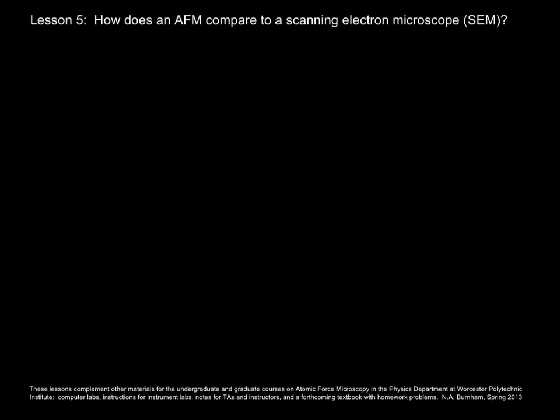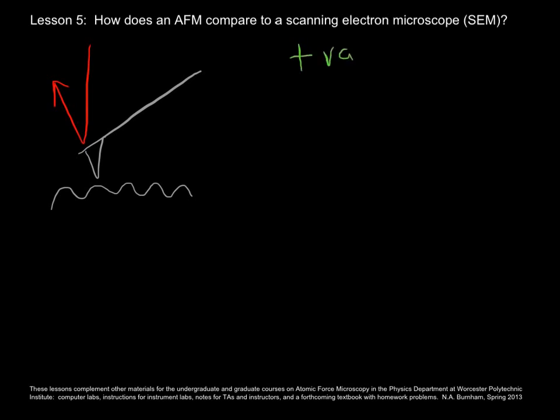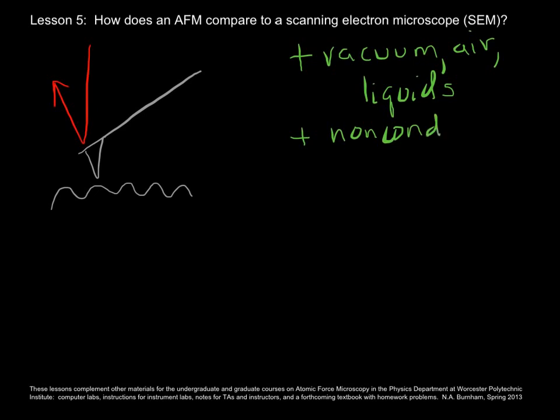Here's a visual reminder of an AFM with the cantilever and laser beam near a sample surface. What's good about AFM? First of all, you don't have to have a vacuum — you can do AFM in vacuum, but you can also work in air and also in liquids. Biologists really like that because you can study living cells. The sample can also be a non-conductor or a semiconductor.